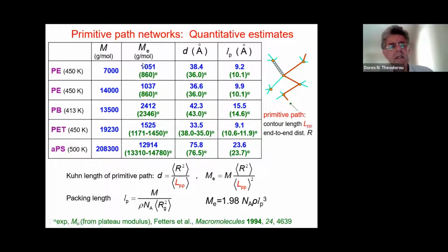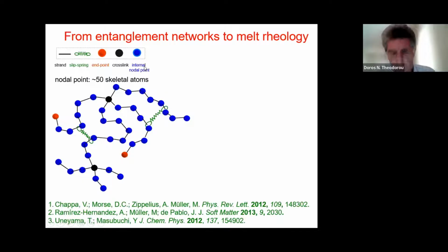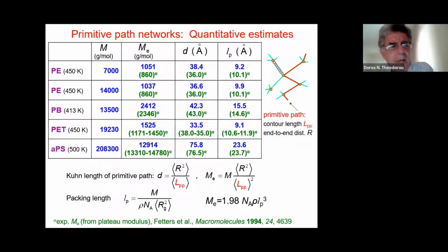And as you can see, the results that are obtained from the topological analysis compare quite well with estimates based on rheological properties. Also shown in the last column here is the so-called packing length, which is obtained from the molar mass, the density, and the mean squared radius of gyration of the chains. And it is essentially a measure of how fat the chains are in relation to how stiff they are. You can see, for example, it is much bigger for polystyrene, which has these phenyl rings sticking out of the chains.